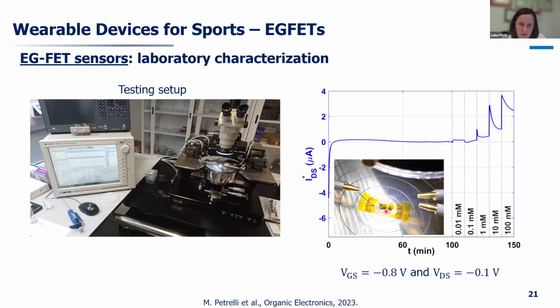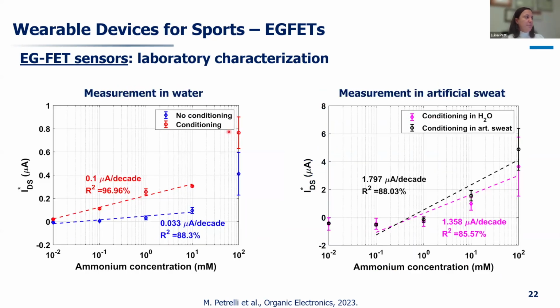This you see a little bit better, this PDMS chamber that I was mentioning. Okay, this is the concentration of interest, and this is the characterization in the laboratory. So we first measured with water, with membrane conditioning and without. So membrane conditioning is always good. We also measured in artificial sweat, conditioning again the membrane in artificial sweat, and we get a pretty linear behavior with a good sensitivity and also good linearity of the sensors.